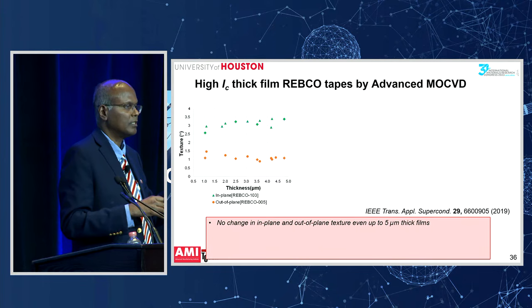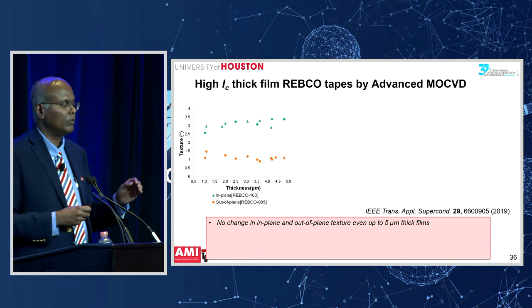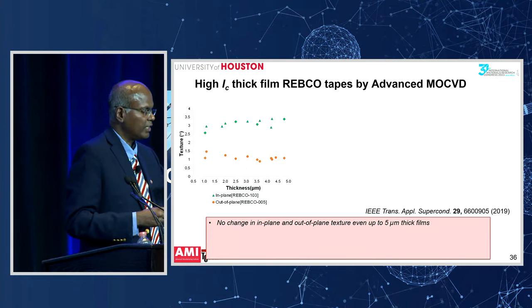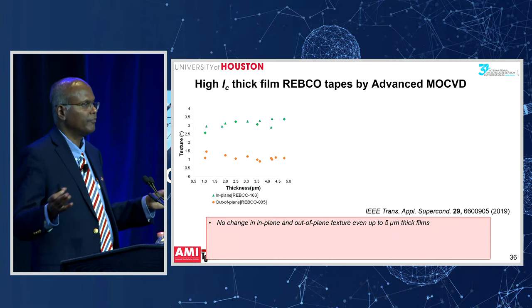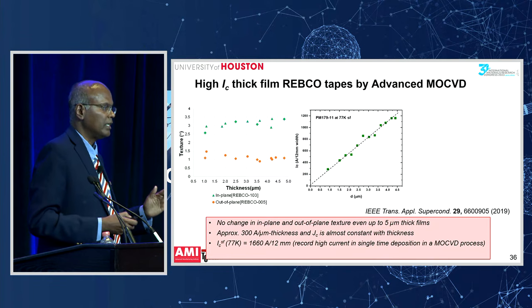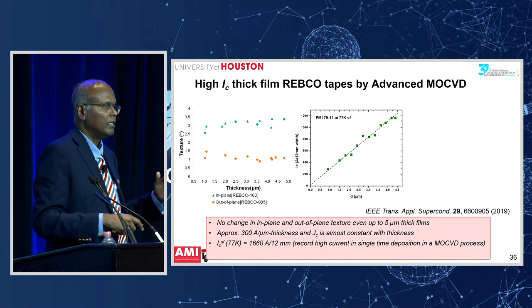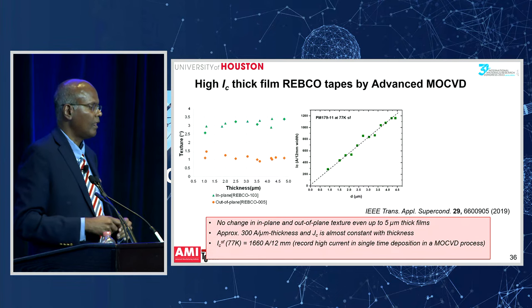And on the chart I'm showing you the out-of-plane texture, basically the texture out of the plane of the film, and then the texture in the plane of the film. You can see in both cases, the texture is maintained almost constant all the way up to 5 microns, right? And then, in contrast to what you saw before, when they increase the film thickness, the currents start to saturate. Here you can see, as you increase the film thickness, the current density keeps increasing, the critical current keeps increasing, even up to 5 microns. And so we're able to actually get some really good performance, even in a thick film.